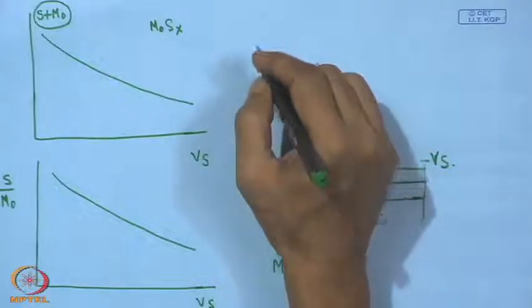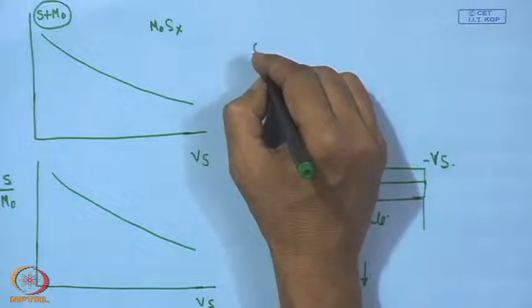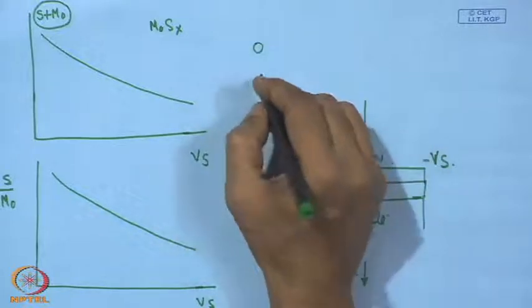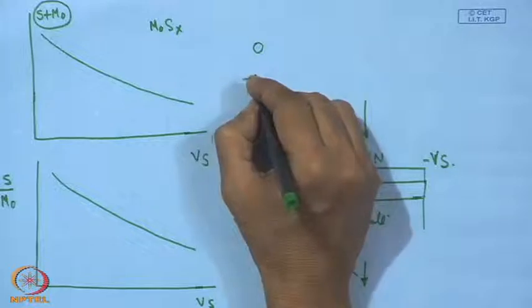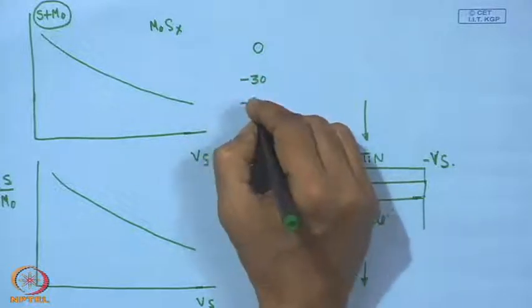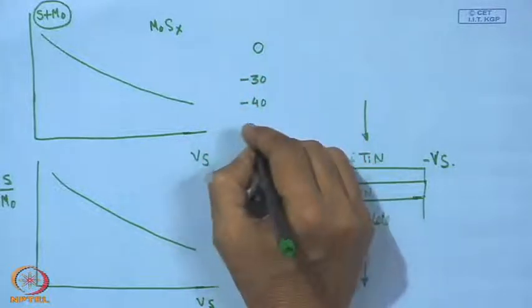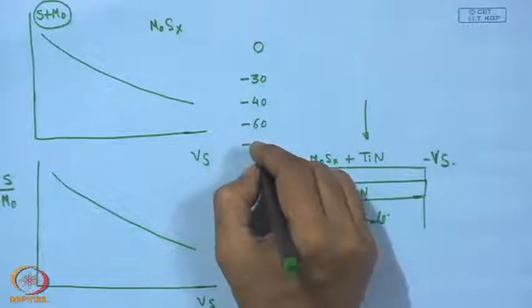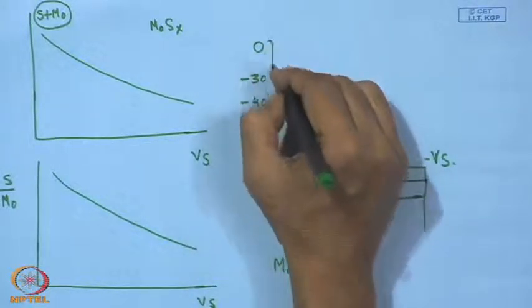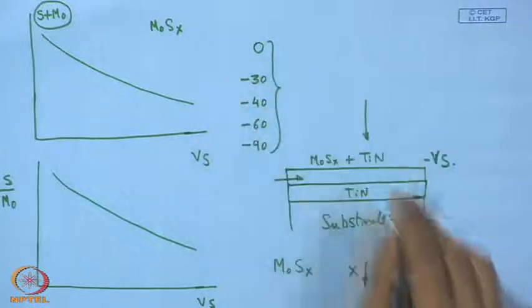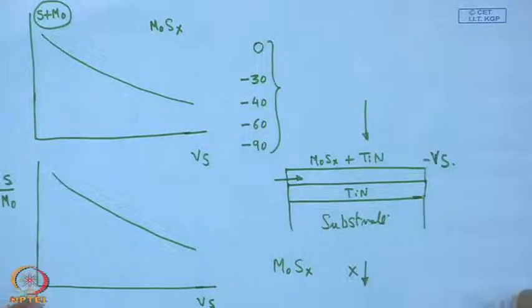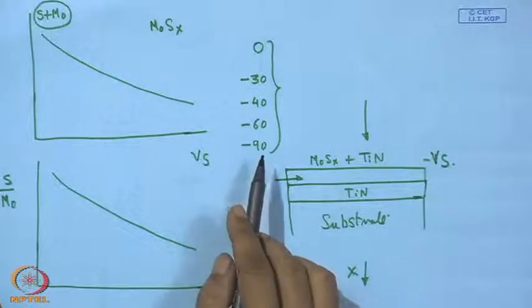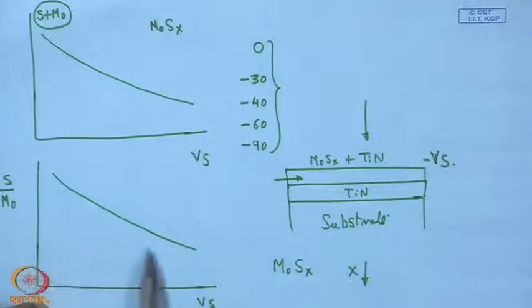So, normally, if one considers increasing the bias starting from 0, say it is minus 30, minus 40, minus 60 and minus 90, this is a range. So, if one tries to examine the effect of the substrate bias voltage, one should have such kind of variation with increase of bias voltage.